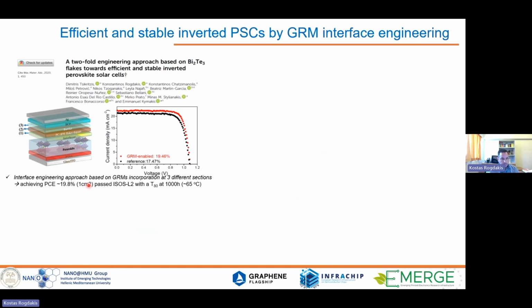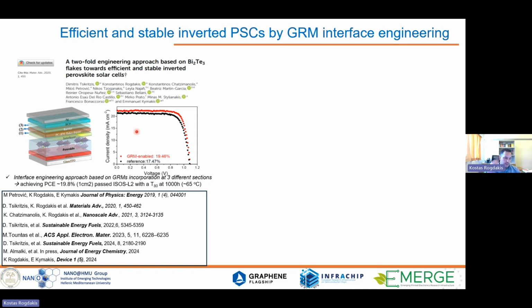As I told you, for the last 10 years we worked on different 2D materials like bismuth telluride, for example. We developed bismuth telluride nanosheets and prepared inks, and we use these inks in order to improve the performance of the solar cell. For example, we test them as a dopant inside the PCBM layer, and also as an interlayer between the PCBM and the perovskite layer. In both ways, we demonstrated improvement in the power conversion efficiency, but also extended lifetime stability while testing the devices under ISOS protocols. Here, for example, we put the sample for at least 1,000 hours inside a chamber at an elevated temperature of 65 degrees. And here is a series of papers that we published in the last few years.